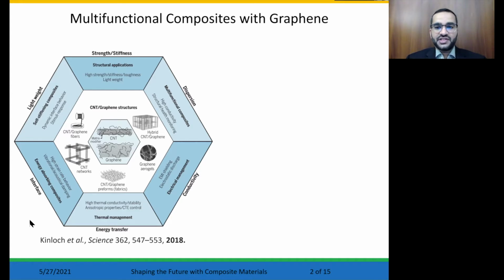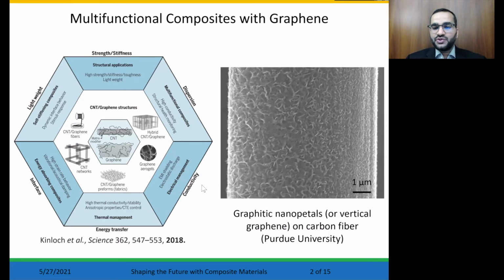Therefore, several approaches have been suggested to improve the preparation of the nanomaterials-based composites, including the production of continuous carbon nanotube or graphene fibers. Today, I will talk about one approach, which is to directly grow graphene vertically on carbon fiber. Unlike the growth of carbon nanotubes, which requires a catalyst layer, graphene grows seamlessly from the single carbon fiber as shown in this image.